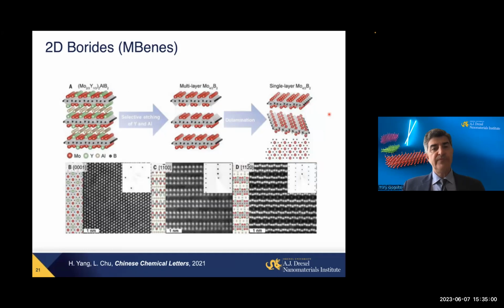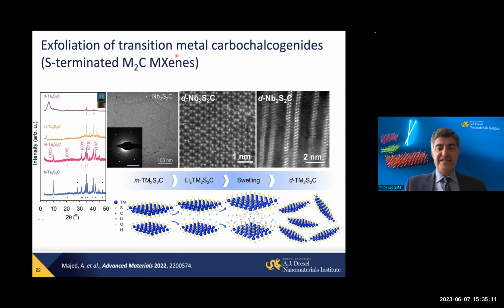And moreover, the system expands further. People showed formation of two-dimensional borides, call them MBenes, for example, MXenes or chalcogenides, dichalcogenides. You can actually have the best of both worlds. It's possible to make MXenes which will have on the surface not oxygen, but sulfur termination or tellurium or selenium. So it's a kind of a carbide terminated with sulfur or another element, you get basically a carbo-chalcogenide. So you get carbide with the surface chemistry like in chalcogenide.